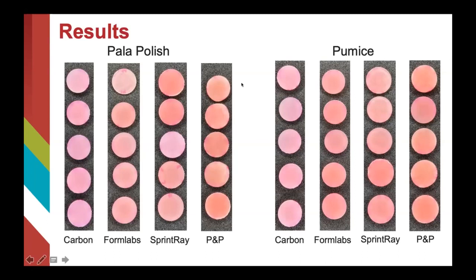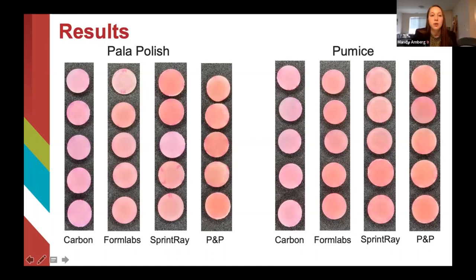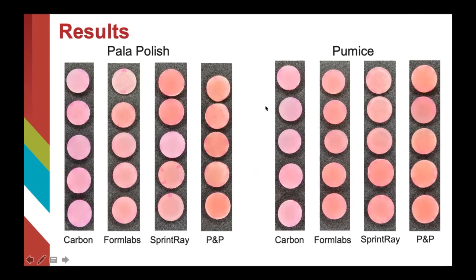Yeah, and another question, something I asked before. When you do the polishing, how do you control the uniformity of the polishing? We wanted to base this on a clinically applicable situation. So we just did the process as if we were polishing a denture in a lab using the rag wheel and whatever polish we were using, so that we could take it back to clinical experiences. Yeah, if you use the disc wheel polishing, it's still very challenging to make them uniform in that short period of time because you probably just polish a part of this disc.